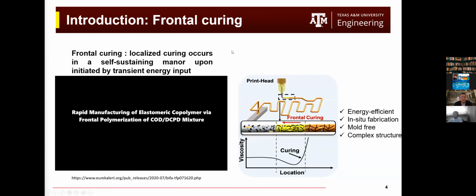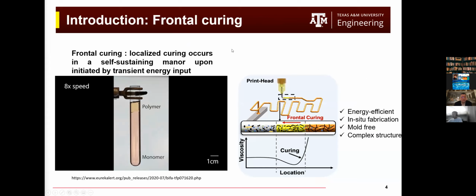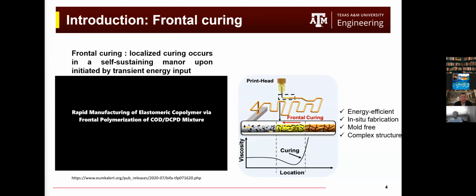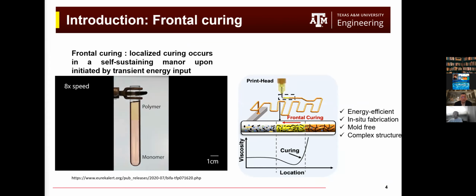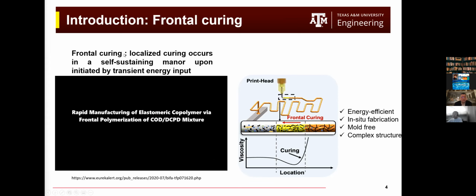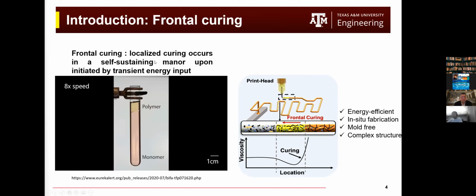And so here we want an energy efficient way to in-situ fabricate the composite material in a mold-free manner. And at the same time, we want it to be flexible in structure design. So one of the interesting solutions to this is using the frontal curing method in 3D printing technology. So I'll introduce the frontal curing here. It is a localized curing that occurs in a self-propagating way, which can be initiated by a transient energy input, as shown in this video.